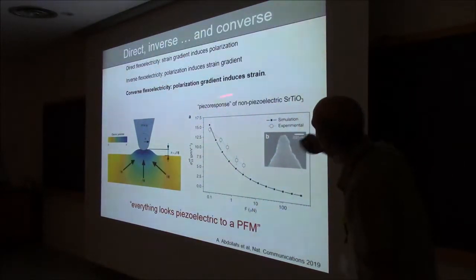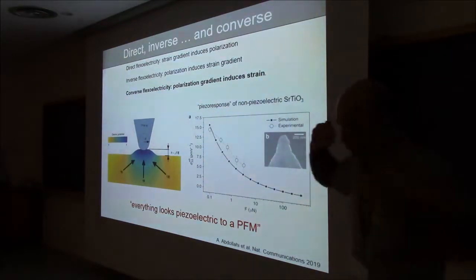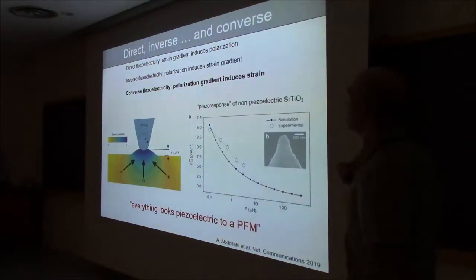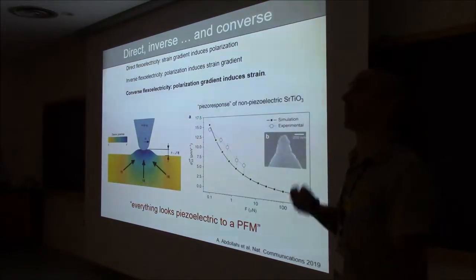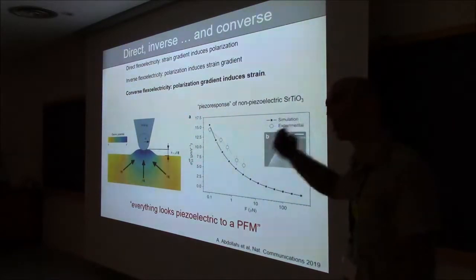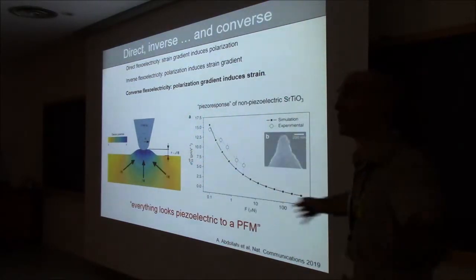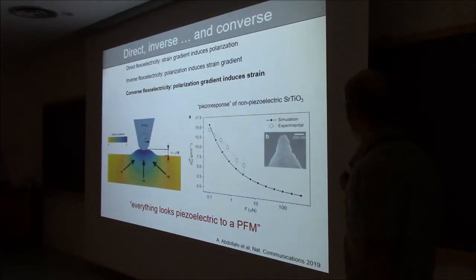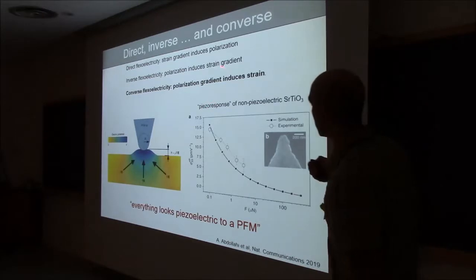Converse flexoelectricity, you try to apply not a homogeneous polarization, but a polarization gradient, which you can achieve by applying an electric field gradient. So if you have an electric field that is not homogeneous in your sample, that will induce a deformation that is linearly proportional to this polarization gradient.